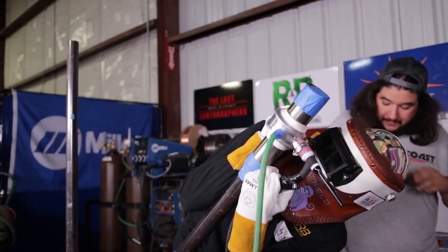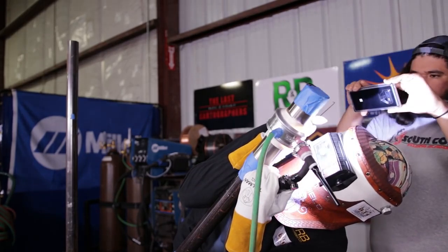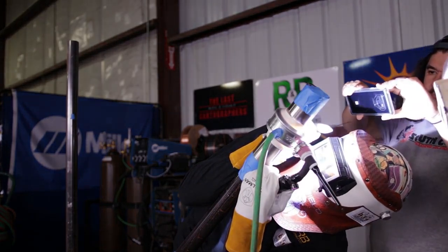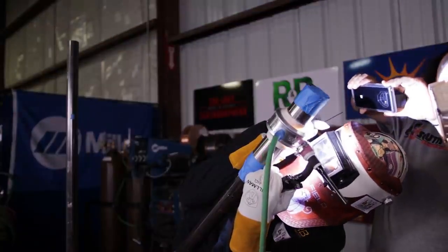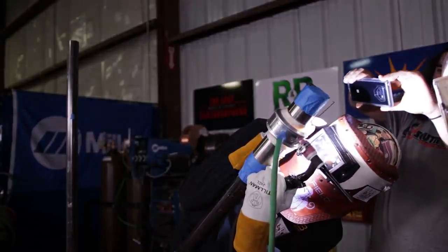I need to figure out what my left hand is doing at the moment. I need to consider that the TIG torch is nothing more than a heat source. On titanium, all I'm doing is keeping the torch on the leading edge rather than the middle of the weld puddle. So I have the torch on the leading edge, I open a keyhole.